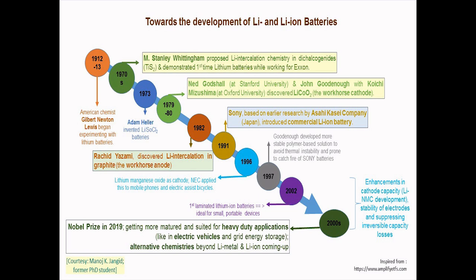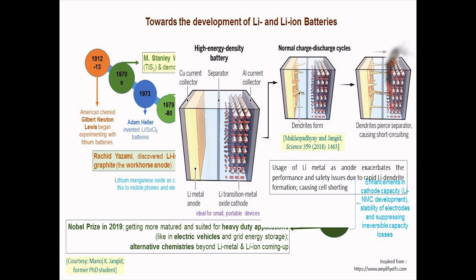in the area of lithium-ion batteries. However, one issue was still not solved, and that was there was still lithium on the other side acting as the anode, which is good, as it will lead to very high energy density for the cell. However, it can lead to plating followed by dendrite formation of lithium, which can penetrate the separator and hit the cathode, leading to short circuit, which would lead to voltage drop and can also cause fire hazards.